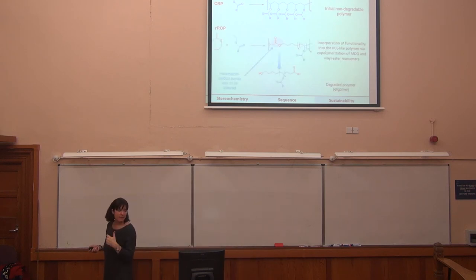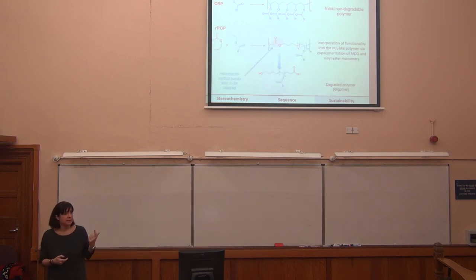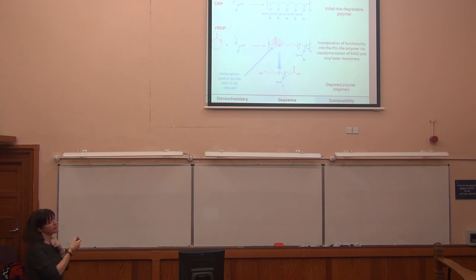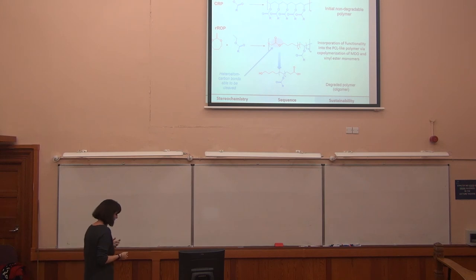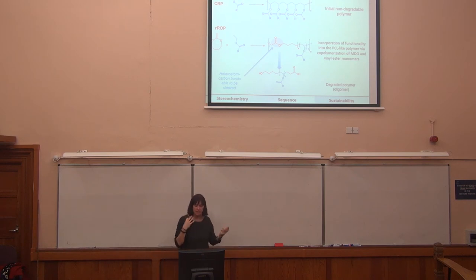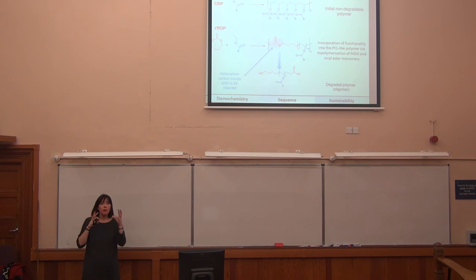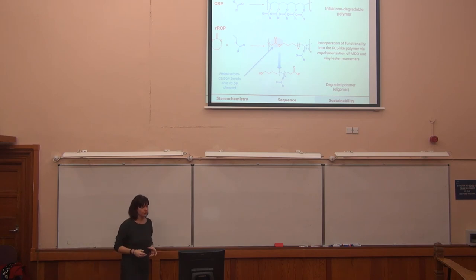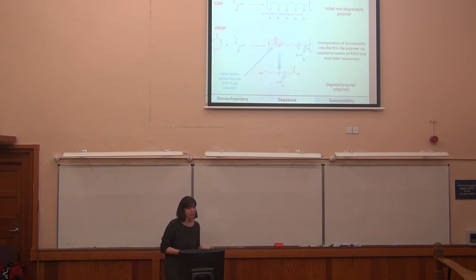degradable. If we co-polymerize and mix in a little bit of this ketene acetal monomer, you actually can selectively introduce these ester linkages into the backbone. The problem is the reactivity of these two monomers is so different, it's so hard to do. So we've had to look at designing new catalysts and conditions and new monomers to try and allow us to do this. And actually, the monomer that we really hit on was polyvinyl acetate, polyvinyl alcohol, which is, as I said, a phenomenally useful polymer.